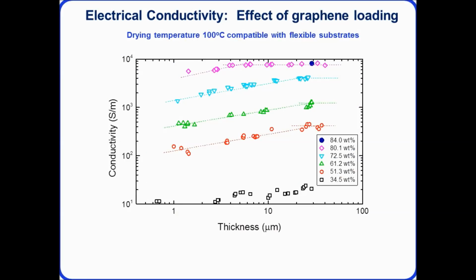We then look at the effect of graphene loading on the film thickness and on the conductivity that we can achieve. And as you might expect, if we have a high proportion of conductive component, we have much higher conductivity, but we always find there's a critical thickness dependent on the loading. So as we get up to the highest loadings, we can achieve this kind of percolation threshold around 2 micron thickness, above which we have a pretty consistent conductivity of the material, so it doesn't increase any further. So we're on the order of 10 to the 4 Siemens per meter.